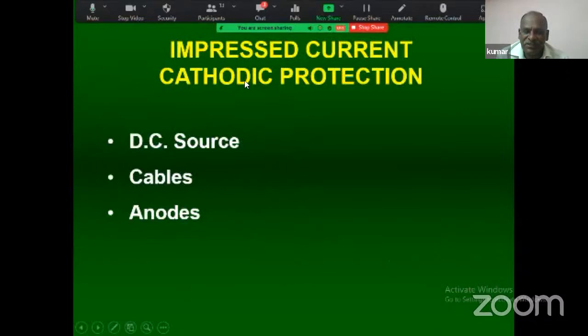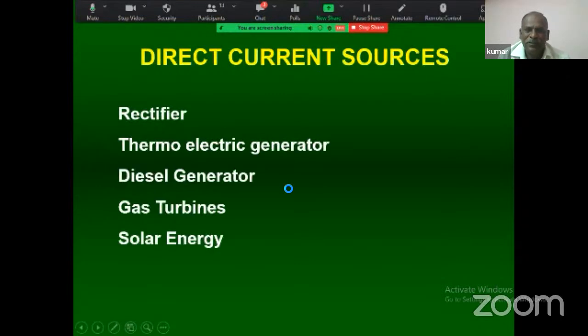If you have an impressed current system, you can have a noble material also, no problem. The only thing is, you have to drive a current, so that whatever electrode you are giving acts as the anode, and noble metals are used. The steel reinforcement is connected as the cathode and it supplies negative current, so automatically Fe will not be released. In that case, our carbon steel is protected. What is required is direct current, through a rectifier or a generator. You can use solar power also.